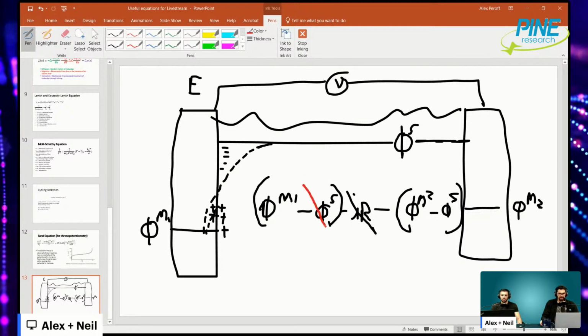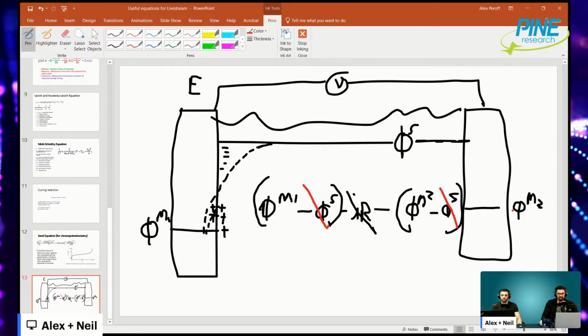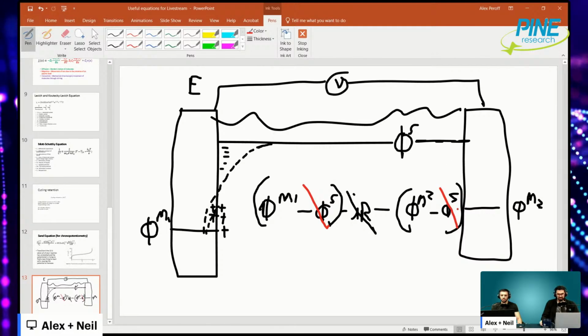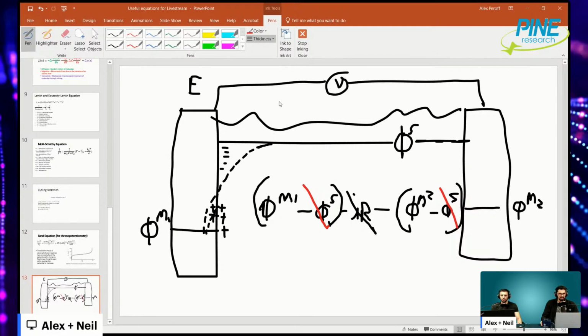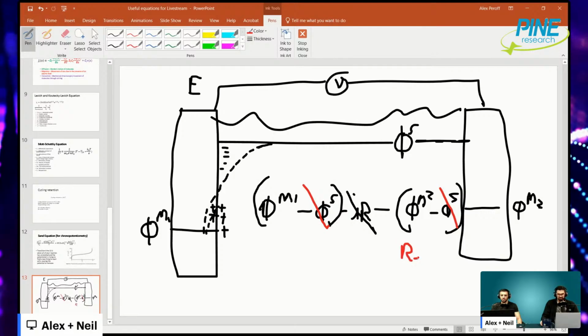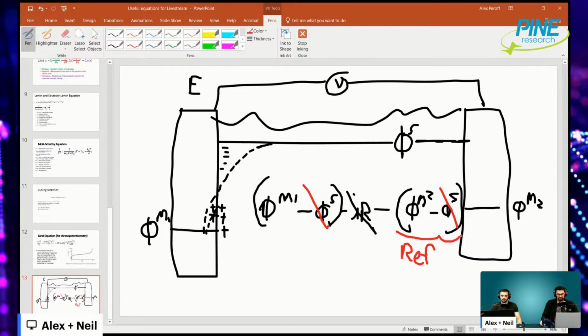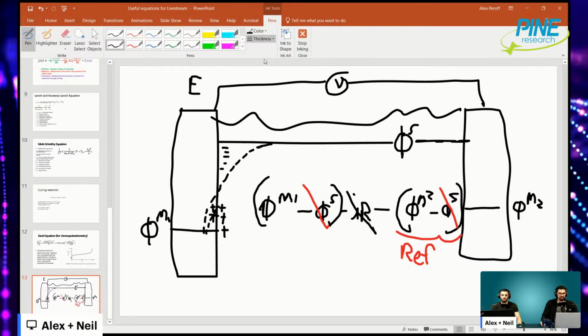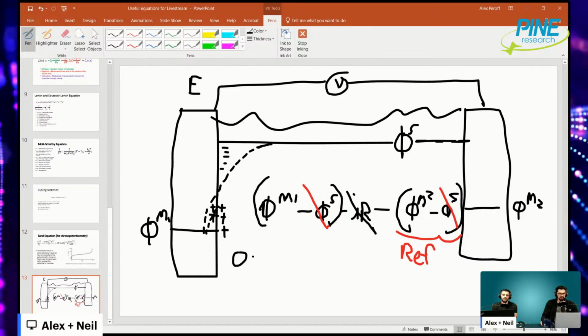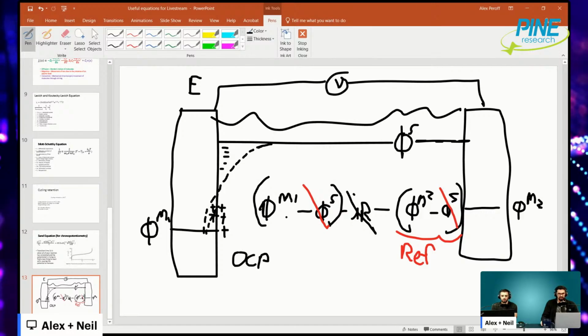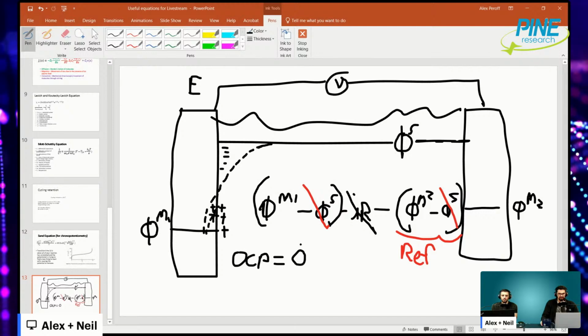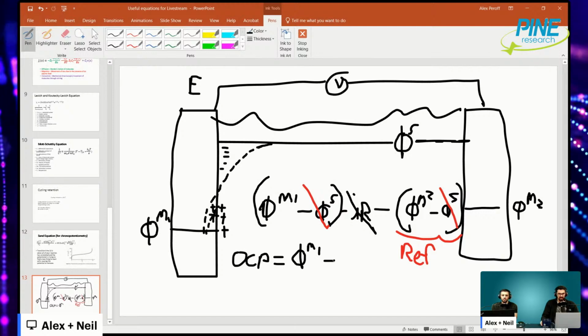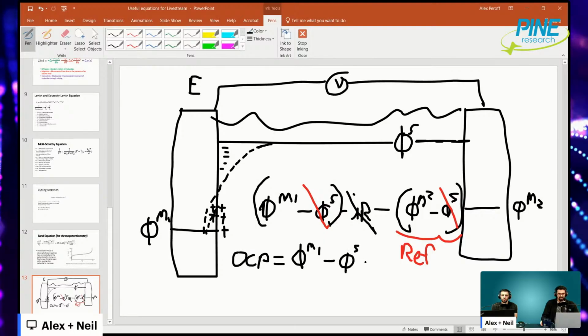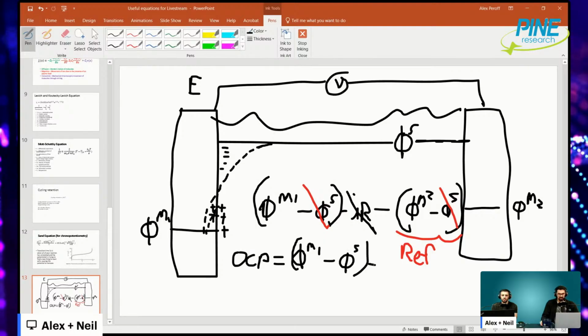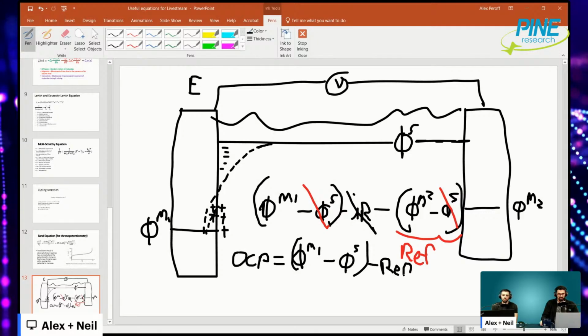But typically what ends up happening is you're not using just any old electrode. You're using a reference electrode. So your phi S is actually different. This whole quantity here that you measure is really the reference, right? That's what this whole guy is. So when you're actually making a measurement, the open circuit potential, because this is all equal to the open circuit potential, is really this phi M1 minus phi S minus the reference. That's really what it comes down to.